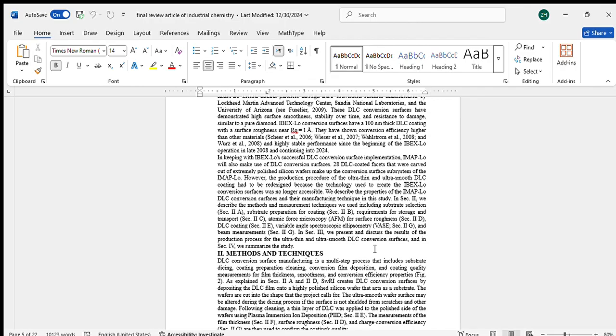During the DLC coating process, it is essential to maintain the cleanliness of the surface. Any contaminant, especially large particles on the surface, can distort the coating and affect its properties. Special care is taken to clean the surface if any contamination is noticed after the coating.